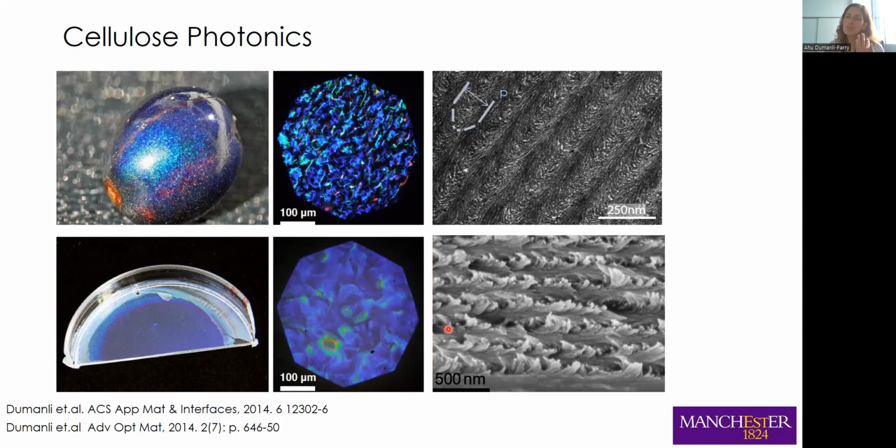What was very striking to us then, when I started this work with Silvia, was that the coloration in the cellulose films was quite digital, which makes sense if you think about these thin films. When you define the pitch, you can calculate it from the cholesteric equation nicely, and it gives the wavelength you expect.